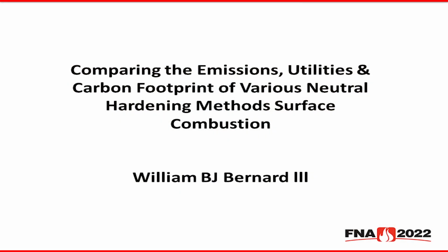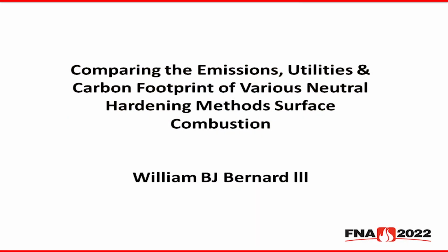So in the end, we have our max heat to load. Max heat to load leads to how fast can we heat it, right? So the more max heat to load leads to the faster heating times, right? So in general, for a 4,000-pound load, this is how much time you would take to heat for each one of these scenarios. And then let's say we're going to soak for 60 minutes, so we have to overcome wall losses and atmosphere losses and other things for about 60 minutes as well to get a uniform temperature within the load. So in the end, this is how much heat energy you're using.